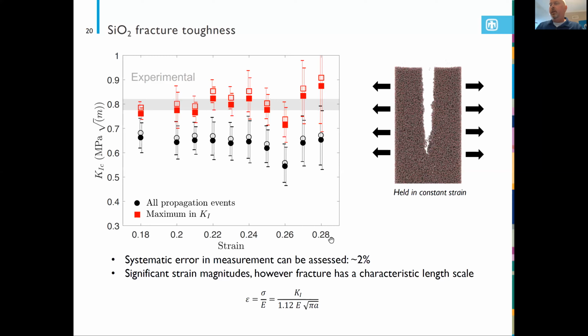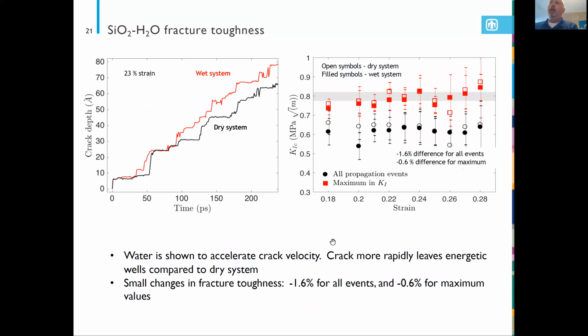Note that these strain values are significant. Once again, this is a feature of the fact that we're operating at nanoscale lengths and nanosecond times. These strain values are primarily chosen in order to have a crack propagate through the material in a reasonable amount of simulation time. These simulations can become quite cumbersome when it takes time to build statistics. Right? So anyways.